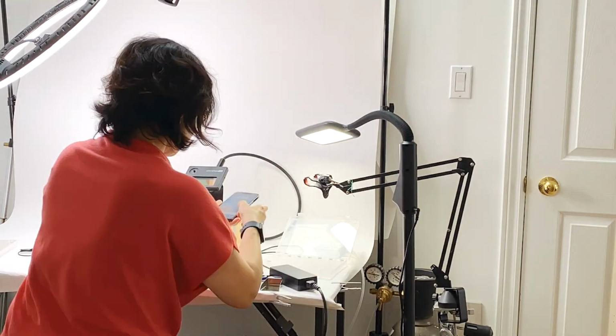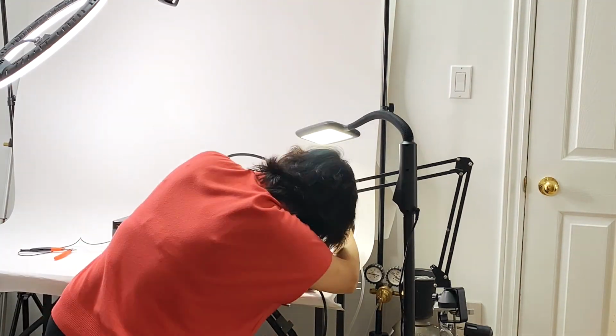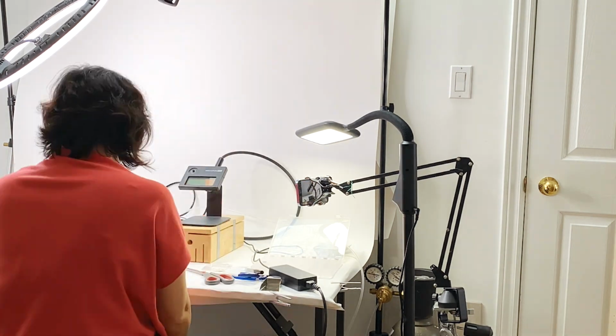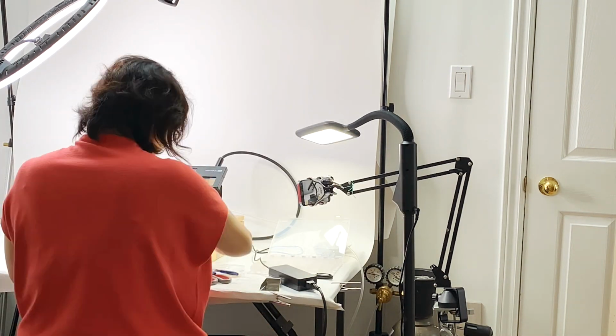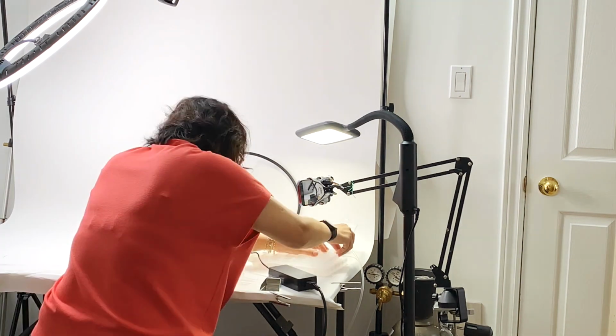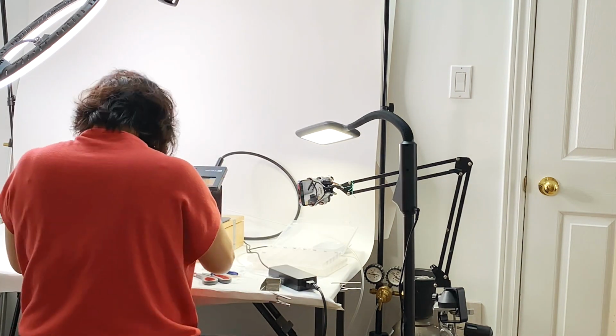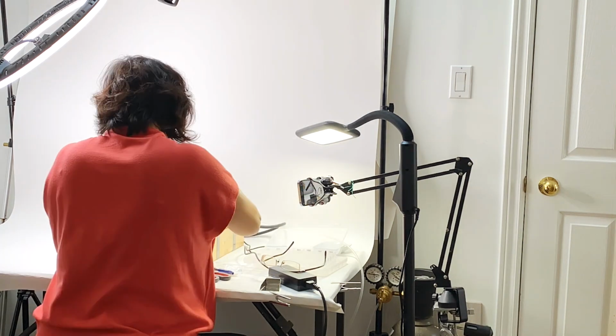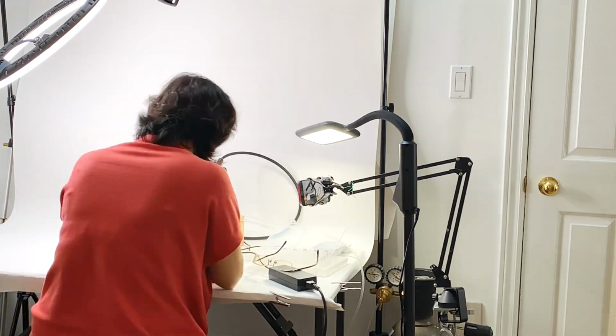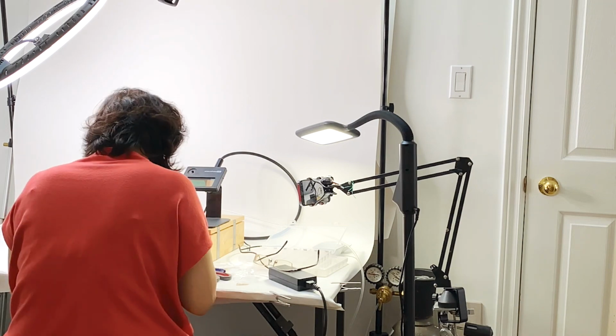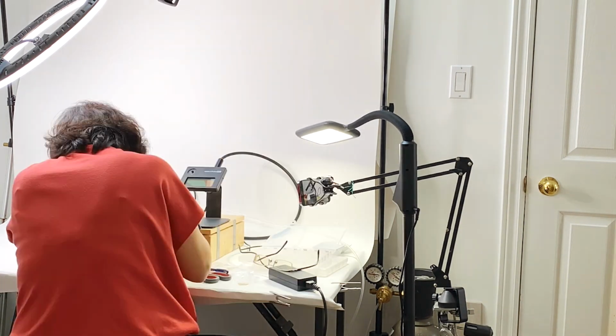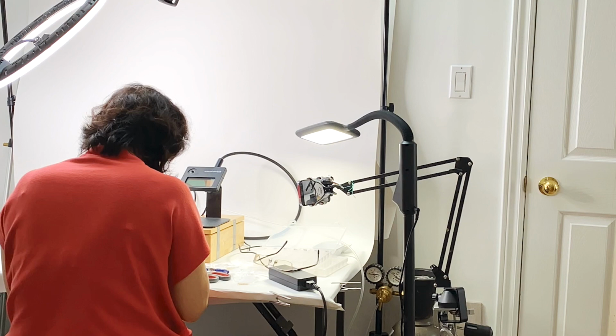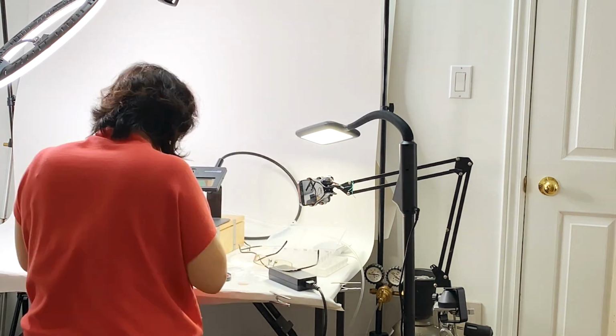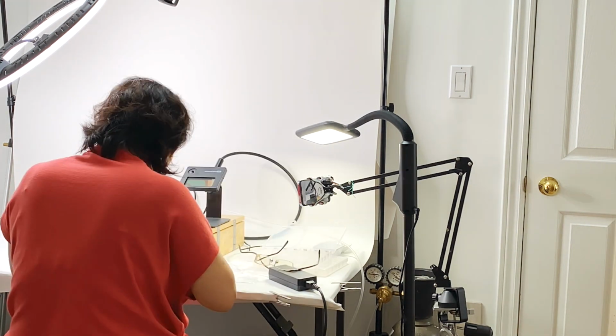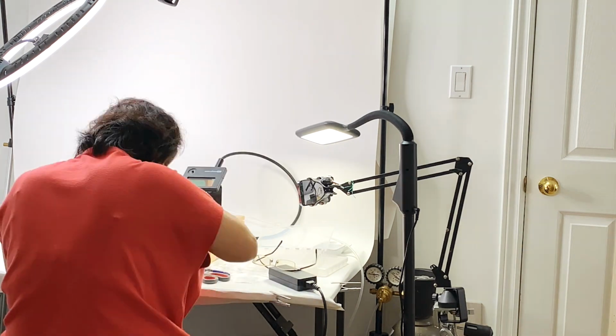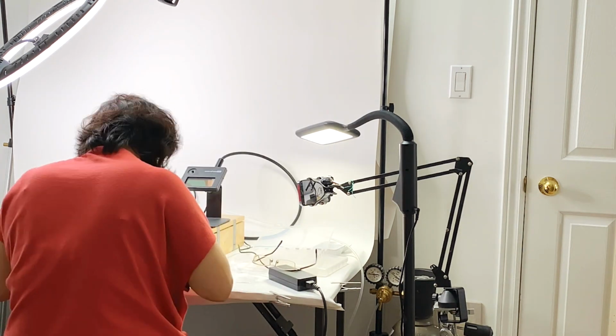Welding with argon gas. I performed the same experiment welding with argon gas and a new electrode to compare. The findings were interesting. Aside from slightly less oxidation, I noticed that the weld result was straighter. Although at higher temperature, welding with argon still did flat top. It did not have the tiny divot that I saw without the argon gas. And also found that it can achieve a slightly more secure weld at the same power setting.